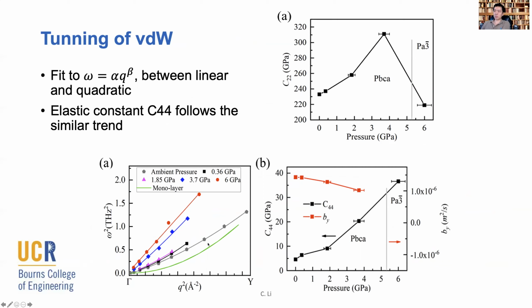And what I'm plotting using the green curve here is what you would expect from an ideal monolayer structure. On the other hand, if you look at a covalent system, you should expect the phonon to be more or less linear, as you can see by this tetragonal calculation under 6 GPa. So it turned out most of our measurements fall somewhere in between. So we fit it with this function, where energy is proportional to wave vector to the power of beta, and this beta will fall somewhere between 1 and 2. It turns out if we do that fitting, for the lower pressures, this value is very close to 2, somewhere around 1.8, until we increase the pressure to be close to the phase transition, but still below it.